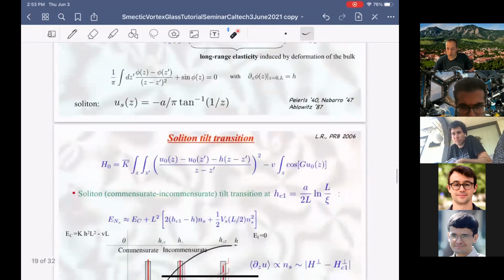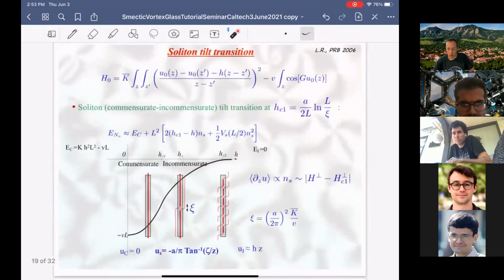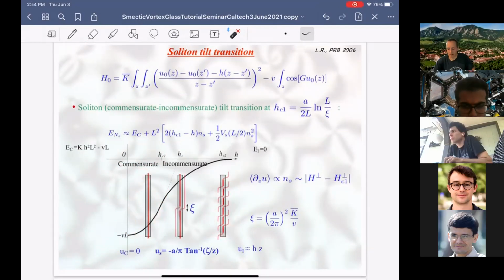So what does this have to do with the tilting transition? Well, when you apply this tilt, here's how you can study the ground state in the presence of this tilt, and indeed what you get is a commensurate-incommensurate tilting transition. So there's a phase in which a vortex line likes to sit in a columnar defect, at small tilting, small transverse field. If the transverse field is large, the tilting is large, then they tilt away from columnar defects. But in between, the process of going from here to the tilted state is by proliferation of solitons, precisely the solitons discovered by Peierls and Nabarro.